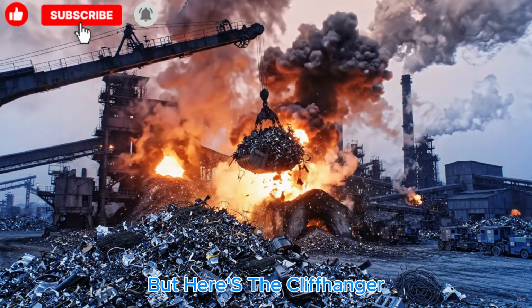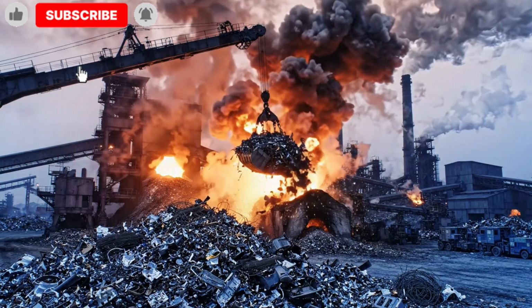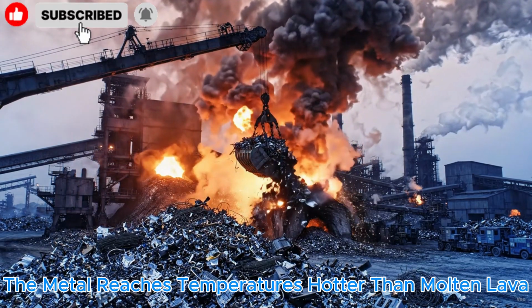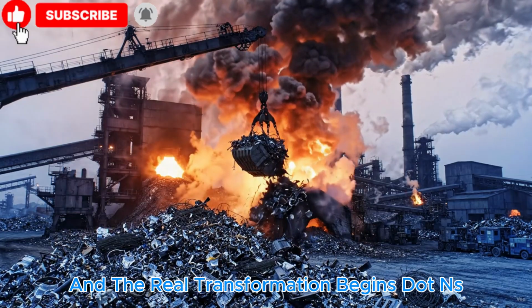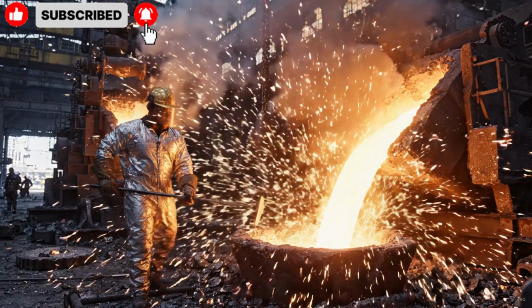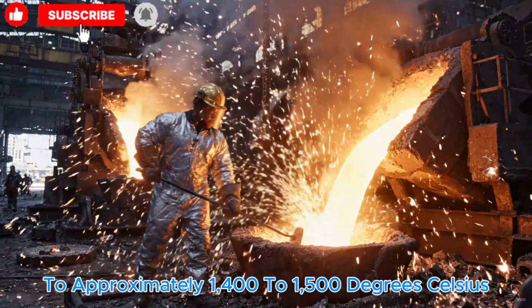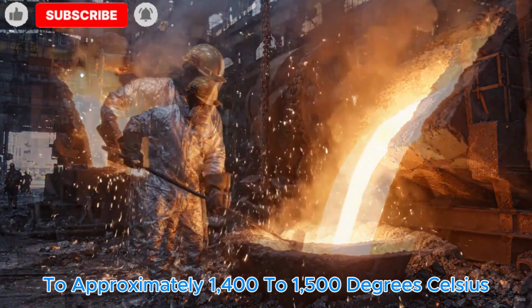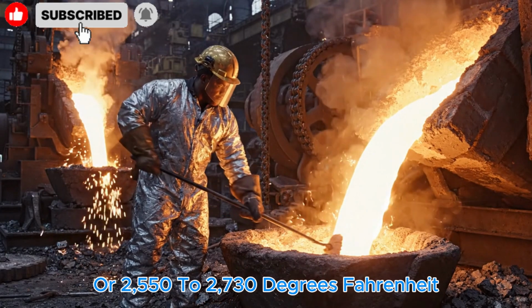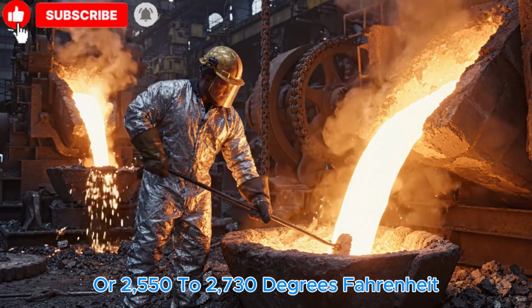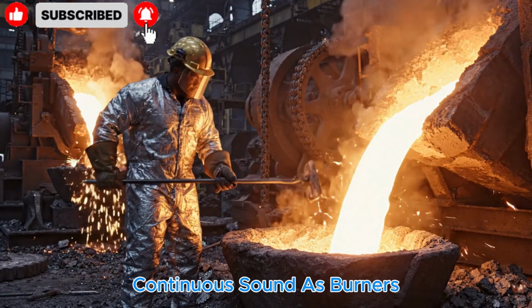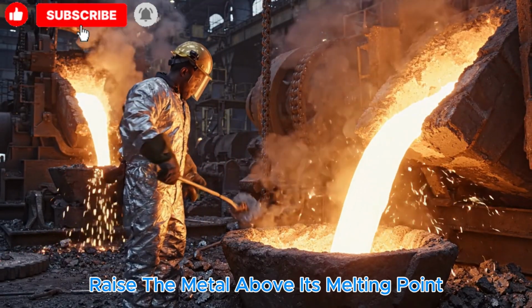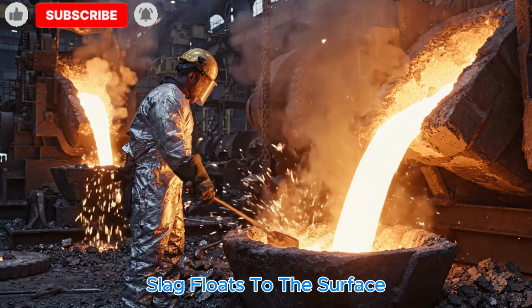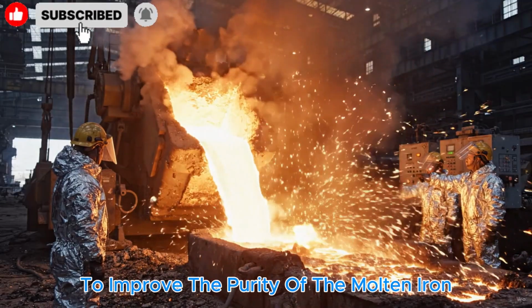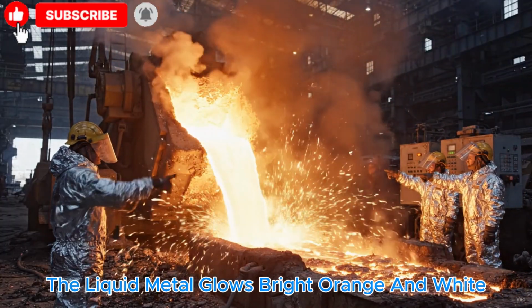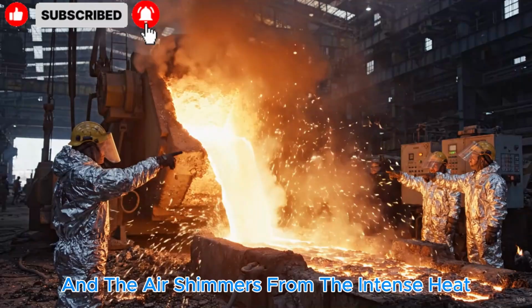But here's the cliffhanger. Once the raw materials enter the furnace, the metal reaches temperatures hotter than molten lava, and the real transformation begins. Inside the melting furnace, the charge heats to approximately 1,400 to 1,500 degrees Celsius, or 2,550 to 2,730 degrees Fahrenheit. The furnace roars with deep, continuous sound as burners or electric power raise the metal above its melting point. Slag floats to the surface, and workers remove it to improve the purity of the molten iron. The liquid metal glows bright orange and white, and the air shimmers from the intense heat.